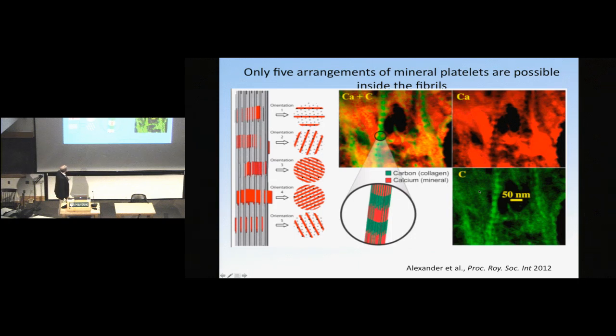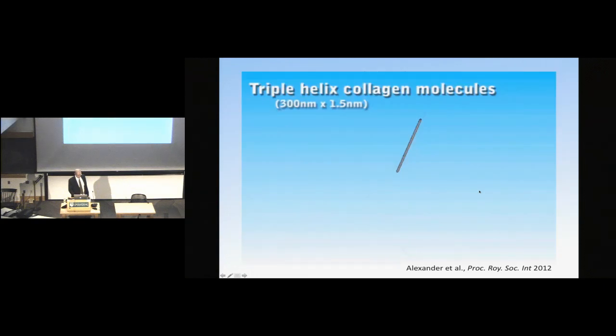And if you take the largest volume fraction and add up how much mineral could be inside collagen, we end up having not enough mineral to account for what shows up when we burn collagen, burn bone in a muffle oven. So I want to very quickly show what this structure is and then talk about its mechanical consequences. Instead, I'll pull up the movie over here, and I want to use this to describe the microstructure.